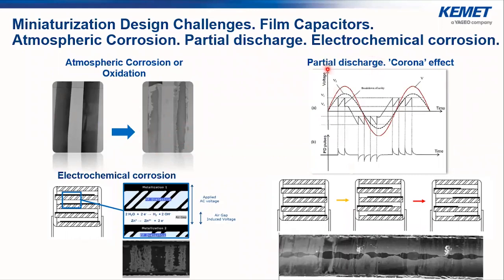encapsulation. About the partial discharge, inside the film capacitors there are small air gaps inside the film windings, as you can see here, at which partial discharge may easily occur under high electric field, and it can lead to electric degradation. Film capacitors operating at mains voltage can progressively lose capacitance as current discharges cause local vaporization of the metallization, and as you can see, the active area is progressively reduced in size, which is visible on the film on the side, with a corresponding capacitance drop.